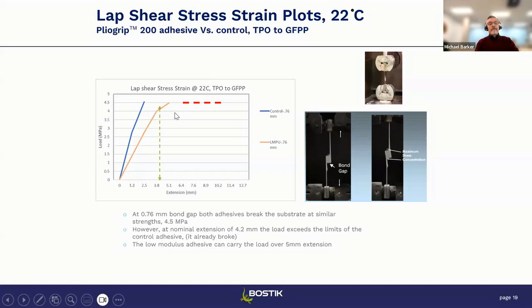But when we take that 4.2 millimeters that we calculated from that engineering equation, and we plot that on here as well for stress strain, we see that at 4.2 millimeters, the high modulus adhesive had already broken. So there is no way this high modulus adhesive would have allowed this bond to stay true when the assembly expanded differentially 4.2 millimeters. So that is fundamentally the advantage of the low modulus adhesive. It is able to elongate and accommodate the differential expansion of the assembly.